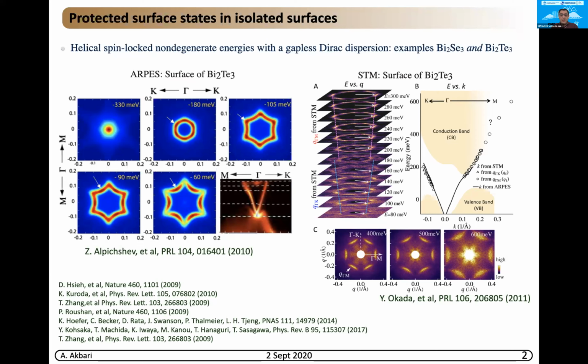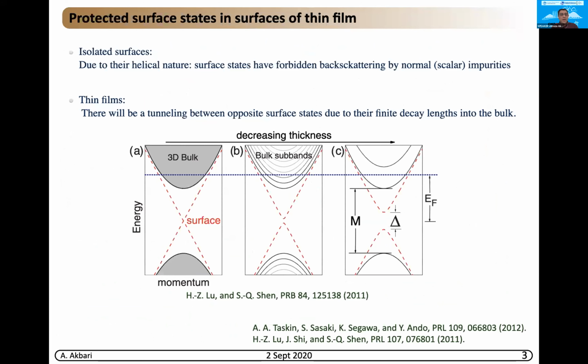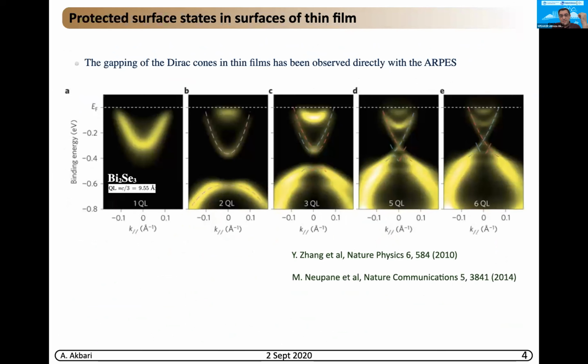Since the opposite layers on top and bottom can talk to each other, we know that this Dirac cone can be gapped, and by decreasing the thickness, this gap becomes wider and wider in the system. This opening of the gap has been nicely seen in ARPES data, for example in bismuth selenide: for a system thicker than 6 QL, you can nicely detect the Dirac cone, and by reducing the thickness, below 5 QL, the gap opens and becomes wider as the thickness is reduced.